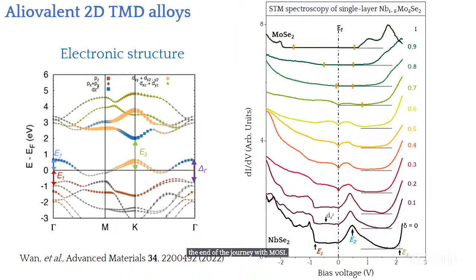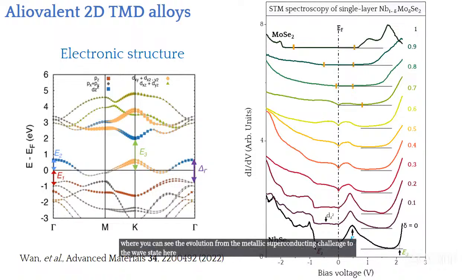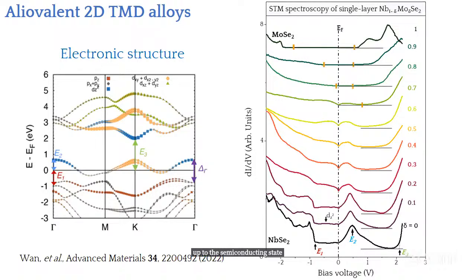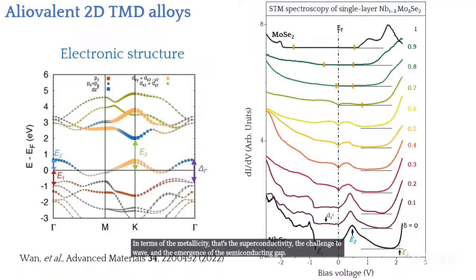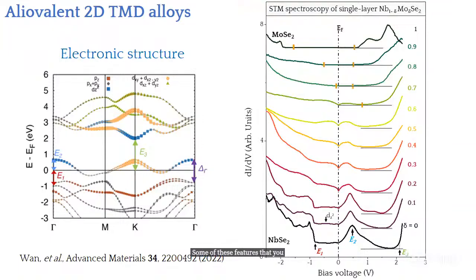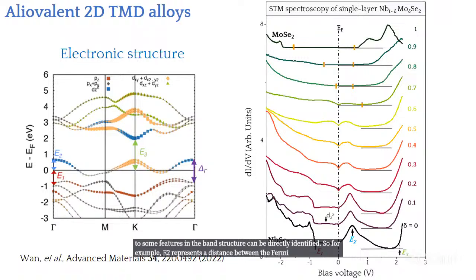Okay, so I'm showing you here a set of representative dI/dV curves where you can see the evolution from the metallic superconducting charge density wave state up to the semiconducting state. So we're able to track the changes in the electronic structure: the metallicity, that's the superconductivity, the charge density wave, and the emergence of the semiconducting gap. Some of these features correspond to features in the band structure, so they can be directly identified. For example, E2 represents the distance between the Fermi level and this point. E1 represents the distance to these p bands, et cetera.